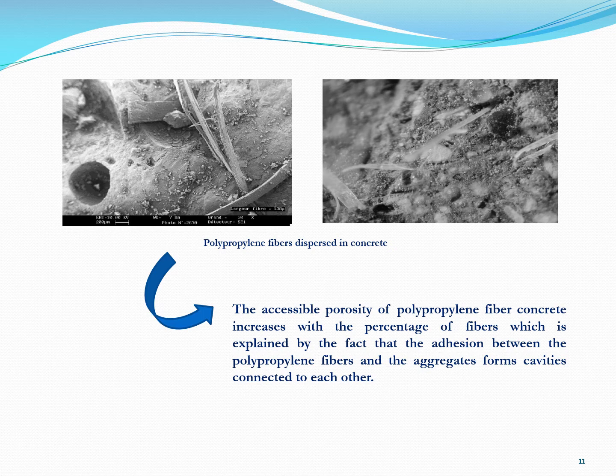In these pictures, we show the polypropylene fiber dispersed in concrete. So the accessible porosity of polypropylene fiber concrete increases with the percentage of fiber, which is explained by the fact that the adhesion between the polypropylene fiber and the aggregates forms cavities connecting to each other.